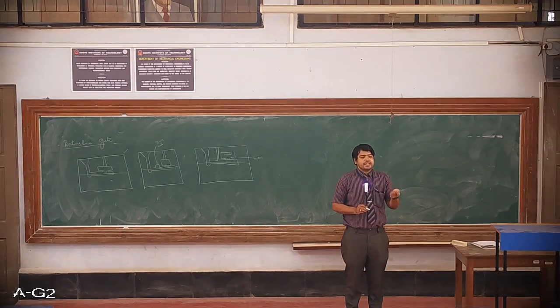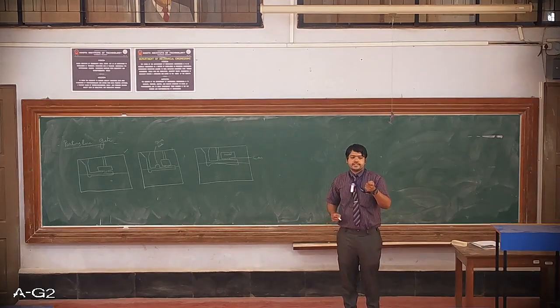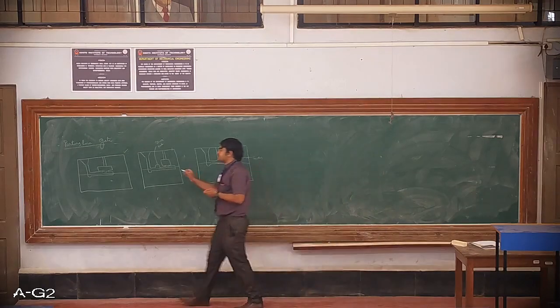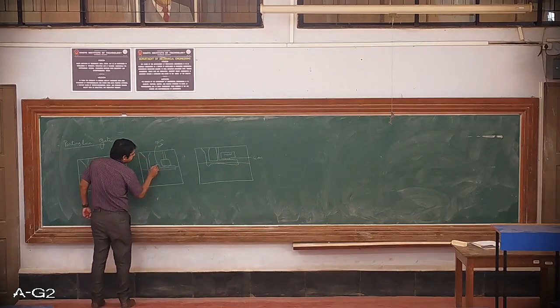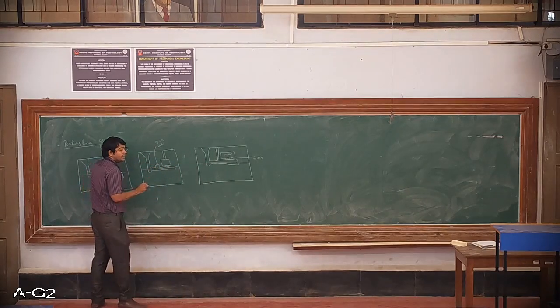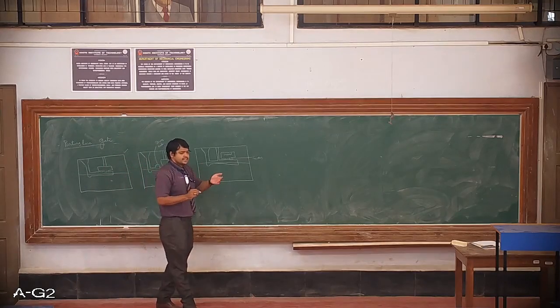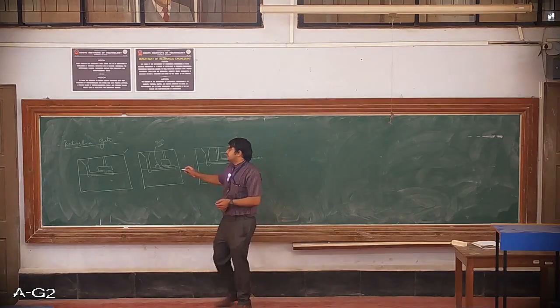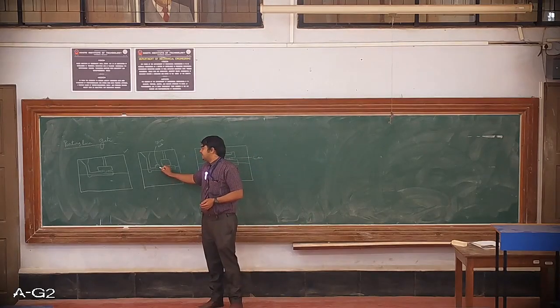Okay, and subsequently they come up as a machining defect as well as they are going to hamper the cutting tool during machining. So in order to avoid that, in most of the cases we make use of something called a skim bob. What this skim bob actually does is the slag will be entrapped over here at the top part, as slag being lighter in weight or smaller in density as compared to the molten metal, it tries to float above, and because of that the slag is restricted over here, and the remaining part of the molten metal inside this